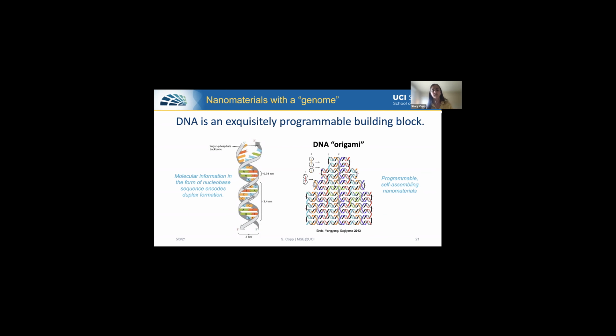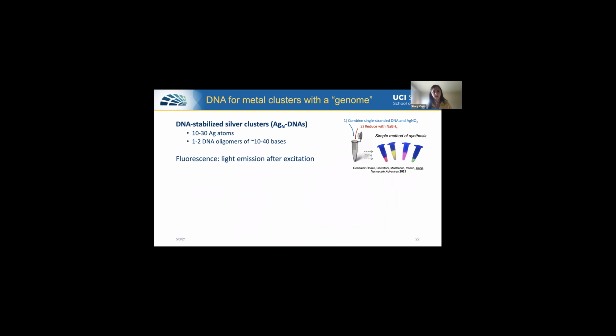We are interested in using DNA as this kind of programmable building block, but specifically we use it to encapsulate those types of metal clusters that I just showed you. So let me introduce you to the DNA stabilized silver cluster. This is the material that we work with. These clusters contain about 10 to 30 silver atoms. So they're very small, only about 1 to a few nanometers in size.